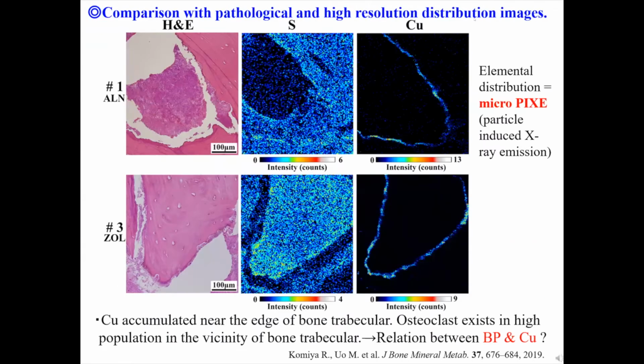Higher resolution elemental distribution images were obtained by a different method called micro-PIXE. In addition, the histological image of the corresponding area is compared. Cu localization was along the edge of the bone trabecula, that is, the region where osteoclasts are accumulated. Bisphosphonate is an inhibitor of the osteoclast, and it also forms a stable complex with not only calcium but also copper. Therefore, a relationship between the copper-bisphosphonate reaction and bone degradation is assumed.